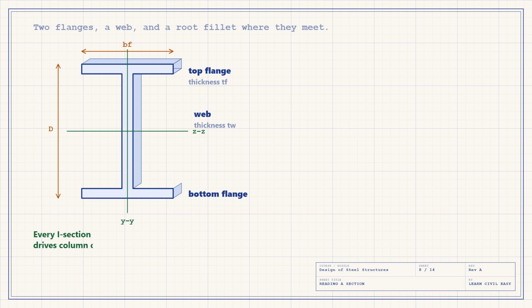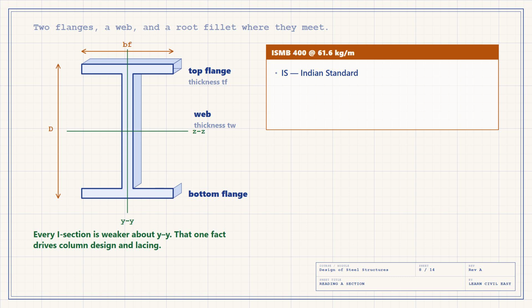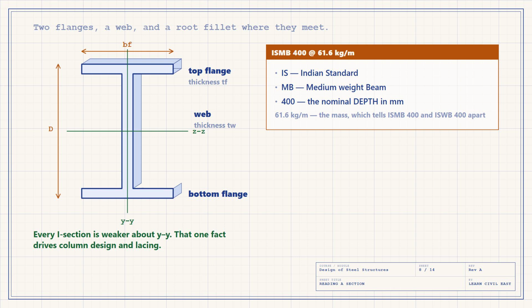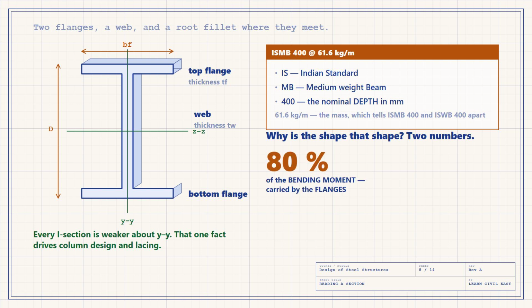Now, why is the section shaped like that at all? Two numbers answer it. In an I section, about 80% of the bending moment is carried by the flanges, and about 95% of the shear is carried by the web. That is the whole design of the shape. Bending wants material as far from the center as it can get, so the flanges are wide, thick, and pushed to the extremes. Shear is carried near the middle, so the web is deep and it can afford to be thin, and it tells you where to add steel. Short of bending capacity, add cover plates to the flanges. Short of shear, thicken the web. Add it in the wrong place, and you have bought weight that does nothing.